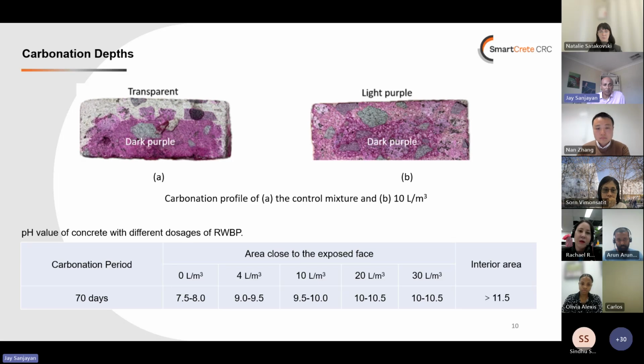So we did some pH tests, because what we can see is a slightly reduced color, because the uncolored area at the top, that is carbonated. The colored area is not carbonated. But with the concrete containing paint, you can see it's not a clear cut. So we did a pH test. So you can see that the carbonated areas, or the color area, it's between 9 to 10 pH, and when we increase the paint dose, the pH is high.